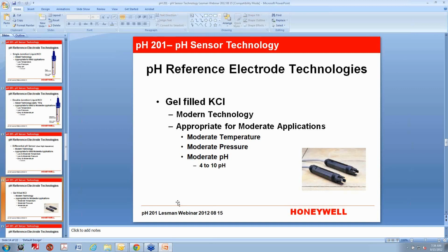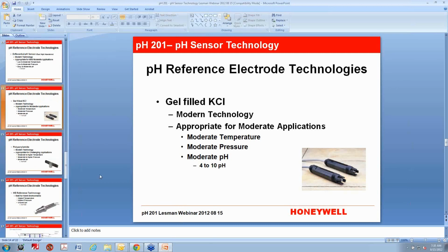So it was a real boon when manufacturers came out with this gel technology. Not all gels are created equal. Some gels don't do well with elevated temperatures and pressures. Some do better. I can tell you that the gel in some of the Honeywell sensors is a gel that will not change viscosity throughout the whole temperature range of the sensor. But some gels do change, so you want to keep an eye on that if you're going to use a gel technology. Again, this is the most common technology, and it's appropriate for moderate applications, so medium temperatures and a moderate pH, say 4 to 10. Now, I've seen these put into applications that are less than 4 and greater than 10. It just depends on the chemistry as to what will work. But again, that's probably the most widely applied type of fill.